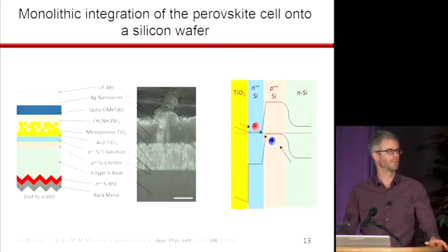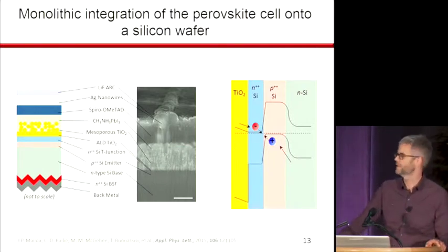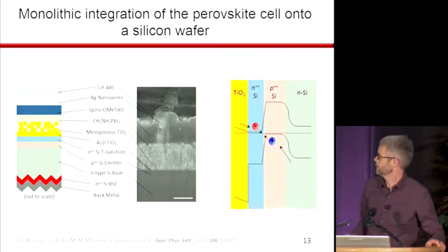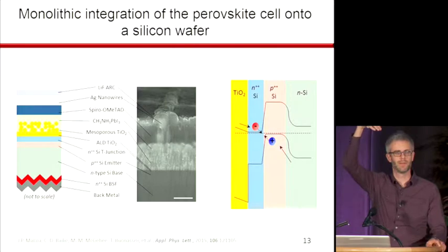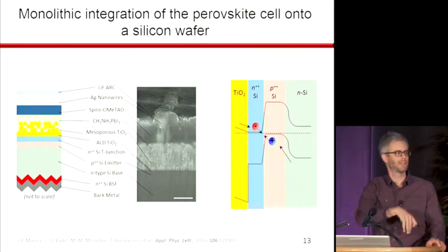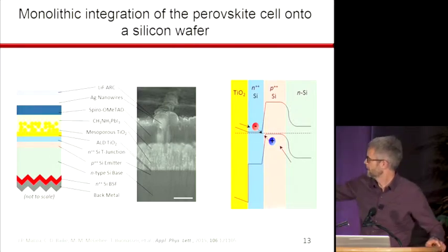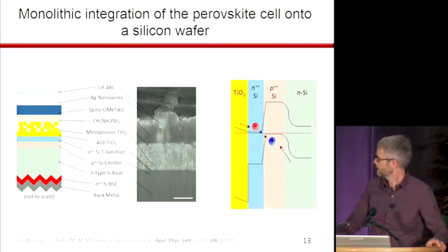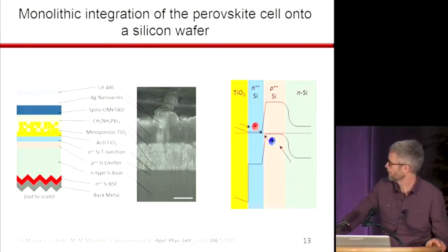Normally when people make perovskite cells, they come in from the other side and the light doesn't go through the spiro-OMeTAD, but we can't do that. Our light has to go through the perovskite cell first and then the silicon, and so we're getting killed there. But that is a solvable problem.